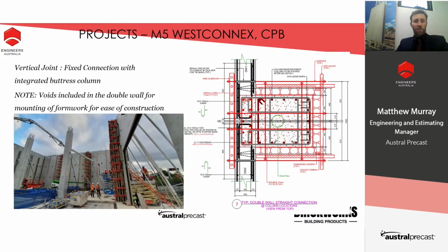From a construction and design perspective, the key thing here is that the fixed connection with integrated buttress column allowed a modular formwork system to be used with the panels. What we can see here on the right-hand side is the 2 double wall panels with a U-bar cast in the end. A prefabricated cage was then placed on site with some of these bars in grey, untied and rotated before the cage was pushed in and before the formwork system was installed. The advantage of this is that it significantly increased the speed of construction for the contractor. The comparable building as an in situ structure took over 12 months to build, whereas this in double wall was approximately 3 months, which is a massive win for the subcontractor.